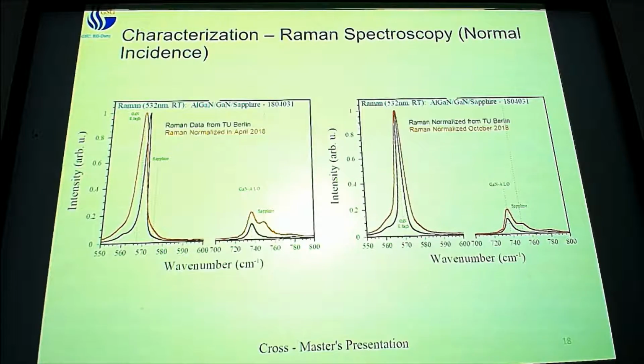So in this calibration procedure, you shifted the peak to match the Berlin data. Is the difference in the widths of these distributions something to worry about? If they were the same system, yes. So the problem with this data, as far as our system versus the Berlin system, is that it's a different type of Raman system. They have better focus than we do. We have micro Raman, I believe. They have confocal Raman microscopy, which means that they have a much smaller focal volume than we do. So although we have a good focus in the XY space, we have a large focus in the Z space. And what that means is that we get information about a taller section of the material than they do. So we are looking at not just the surface, but we are also exciting further down into our materials. So we can get a larger distribution of values for the full width half max because there are more distributions of phonons affected by the light.